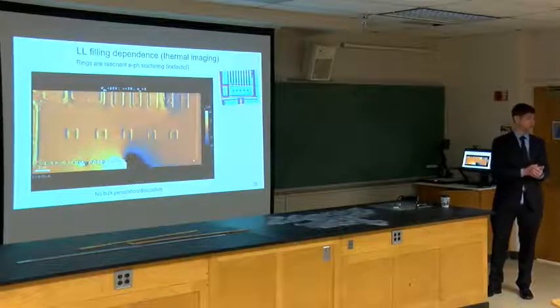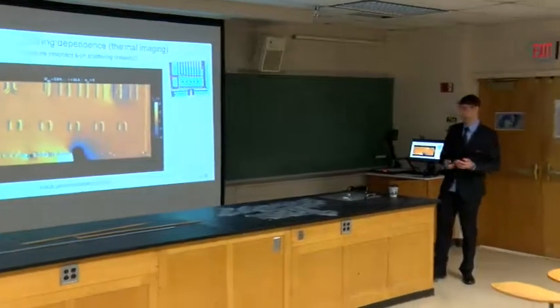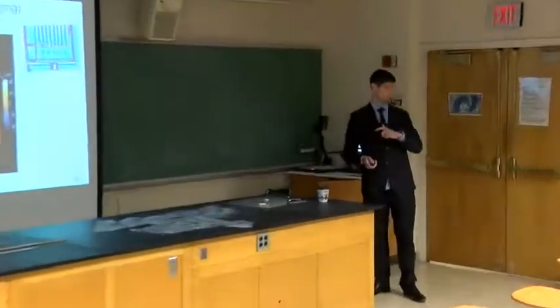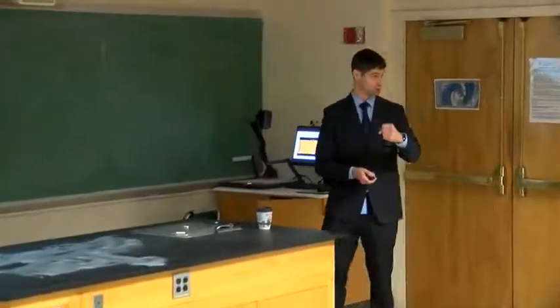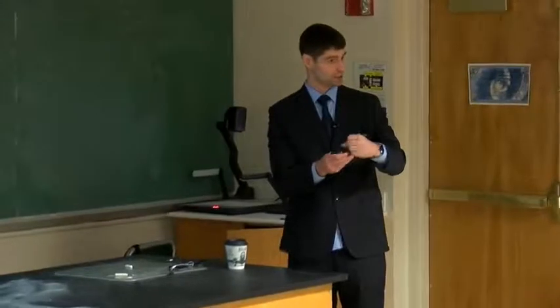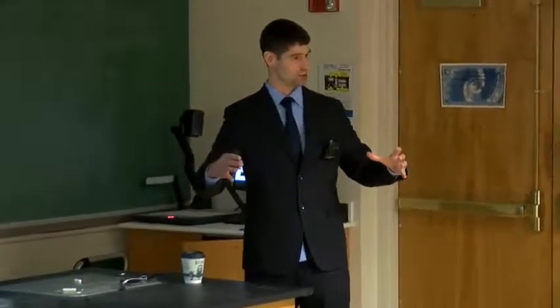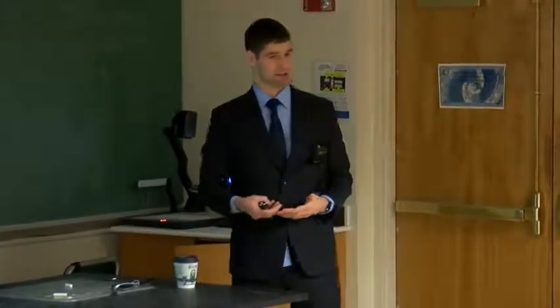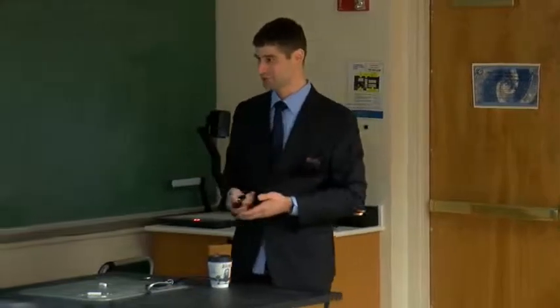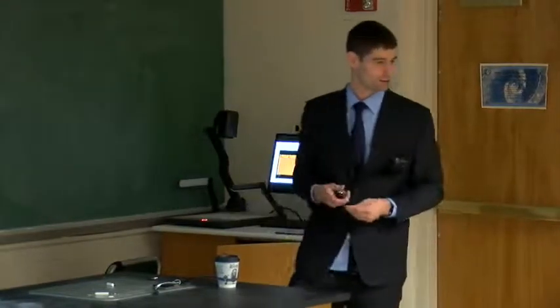Are the rings the same size as your resolution? The minimum size of the ring would be, yeah, but it would also depend if you apply a much larger, like essentially top gate, you would be impacting a much larger area, so you'll get a very large ring. But at the minimum, yeah, we could see 40 nanometers if we look closely enough.